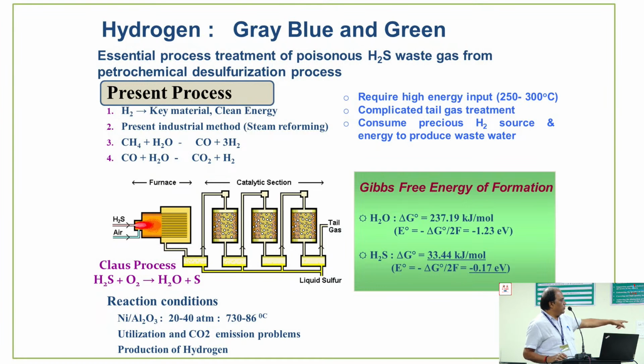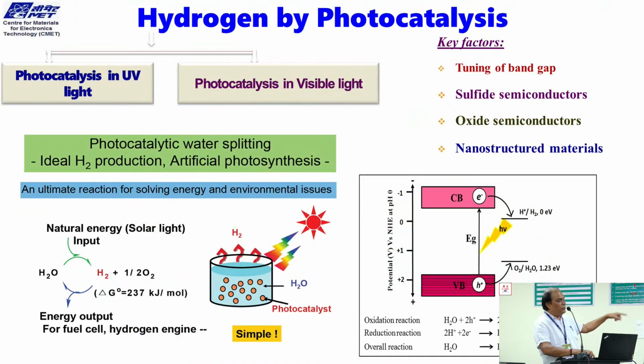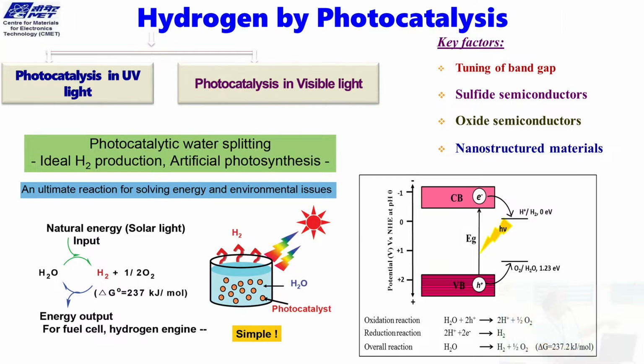So this H2S process which we have developed: a lot of H2S is generated during refining, and whether this H2S can be utilized for hydrogen production. So we have produced hydrogen and sulfur with some of these techniques, and we found that the photocatalytic technique is a good technique where we can produce hydrogen at a cheaper rate. So this is the hydrogen process we have developed, where at room temperature we can produce hydrogen from water. You get hydrogen and oxygen here. So this is actually based on the photocatalytic process.